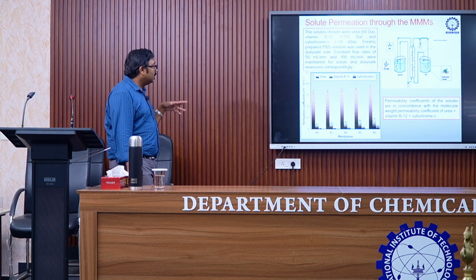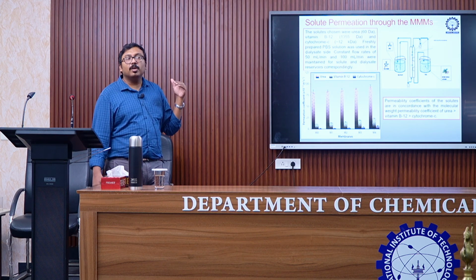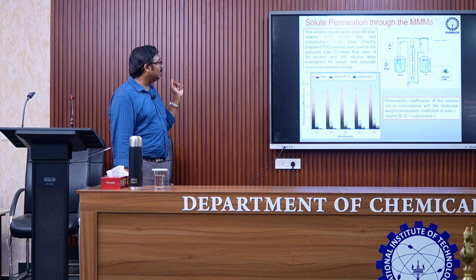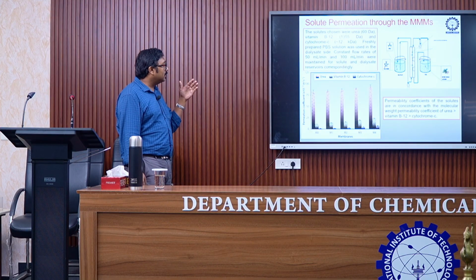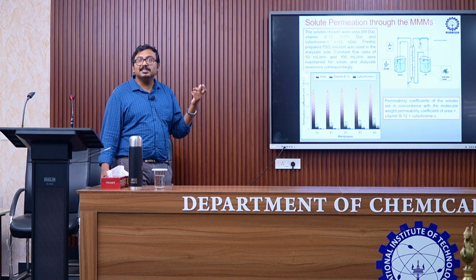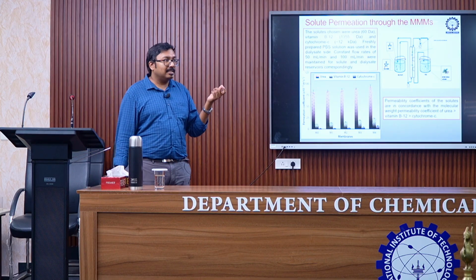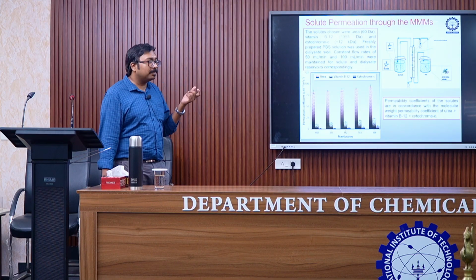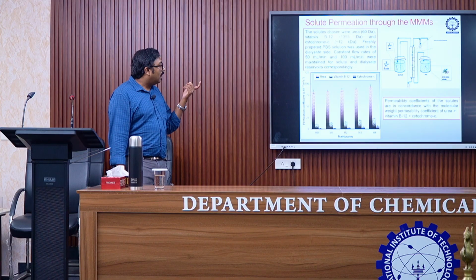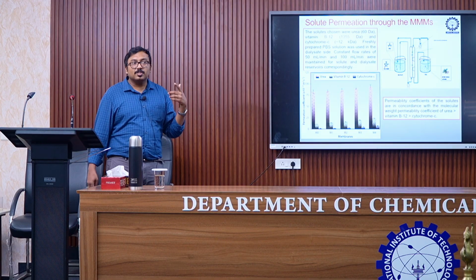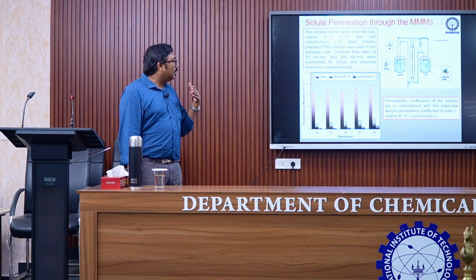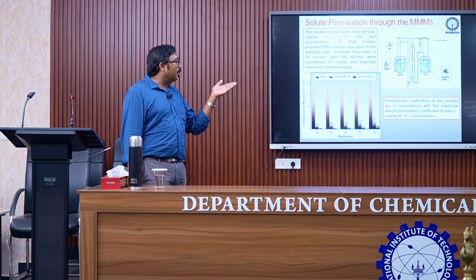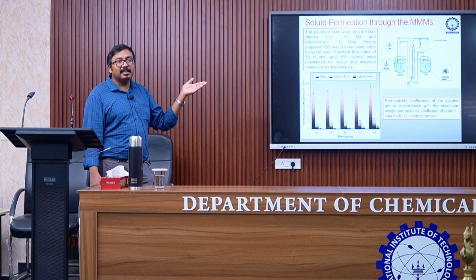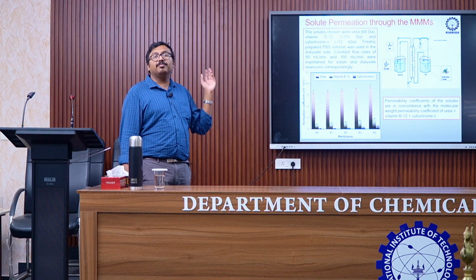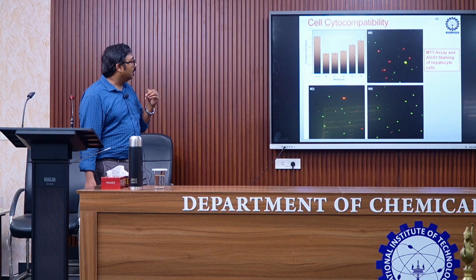So the permeation coefficient, obviously smaller molecules migrate faster. You have very high rates of permeation coefficient, but as the size increases, an exponential decrease in the permeation coefficients could be seen. And as expected, permeability of urea is greater than B12, greater than cytochrome C, which is in the order of their molecular weights.